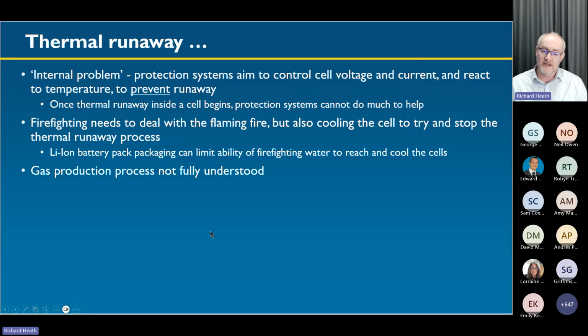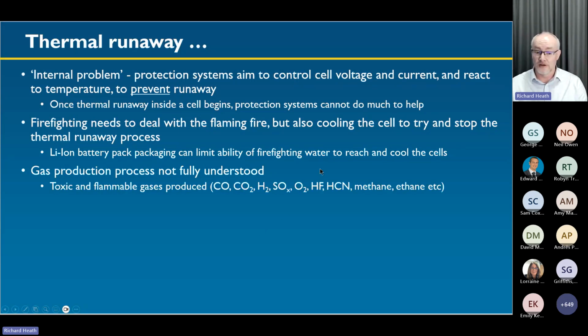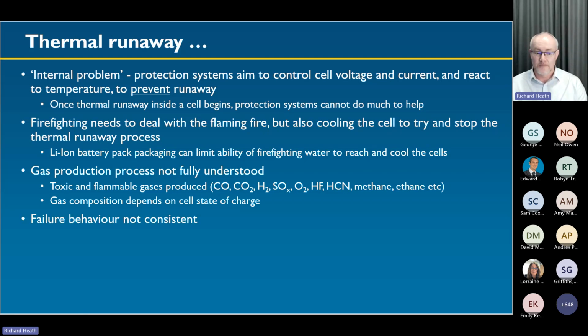And the process through which the gases are produced during thermal runaway is still not really fully understood. Although what is known is it's quite a nasty mix of gases. You've got carbon monoxide, carbon dioxide, some hydrogen, various sulfurous oxides, oxygen, hydrogen fluoride, hydrogen cyanide, methane, ethane, amongst others. So when they fail, that cloud of white gas that comes out is quite nasty. And the actual composition you get seems to depend on the state of charge of the cell. And the failure behavior is not entirely consistent either.